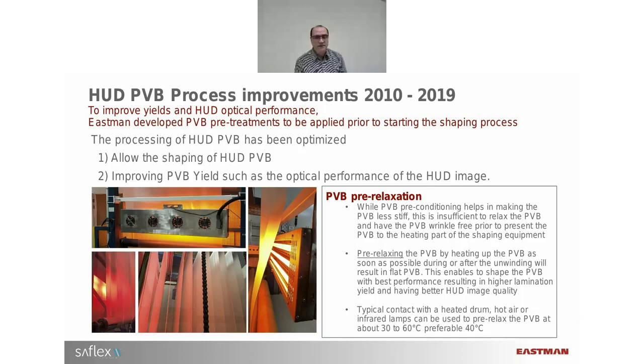Pre-relaxation, what does it mean? It's heating up the PVB between 30 and 60 degrees as soon as possible after the unwinding. So it can be before an accumulator. If you don't have an accumulator, it can be after you have been splicing the PVB rolls, but as soon as possible, giving the PVB the time to act and to become fully, let's say, pre-relaxed, prior to heating it up to the shaping temperatures of the lamination line.